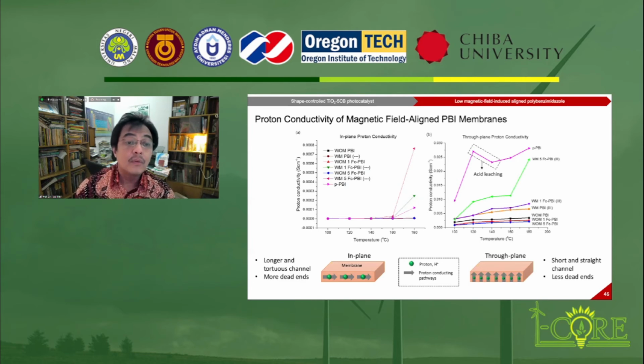However, at 140 degrees C, a sudden decline in the through plane proton conductivity was observed.